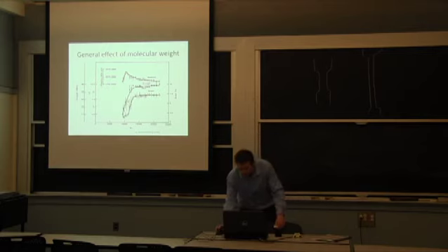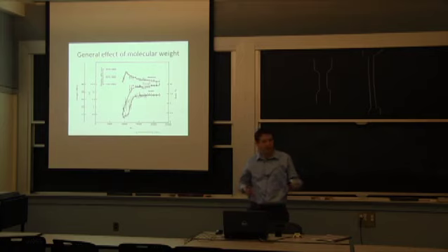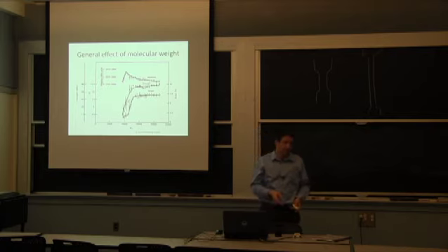Well, if I look at it here, this may or may not be the best example, but I can take this point on the strength curve, and I have a strength that's about 12.5 KSI, and then I keep going here, and I have a strength that's maybe 15% less. Somebody may say, well, I like the 15% more. That's my test. That's what I'm choosing. But we're looking here at a difference in molecular weight of about 60%. All of that will show up in creep, not in the tensile test.